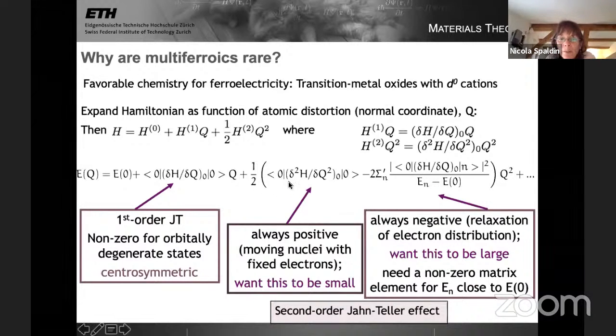And the first term is always positive, and it corresponds to moving the nuclei without letting the electron density change from the zeroth order system. You see that the wave function stays in its zeroth order undistorted state. We try to push the ions towards each other, but we don't let them rehybridize. And so this is energy raising, and of course we want this term to be small. The second term is negative, so this term we'd like to be large, since it's going to lower the energy.